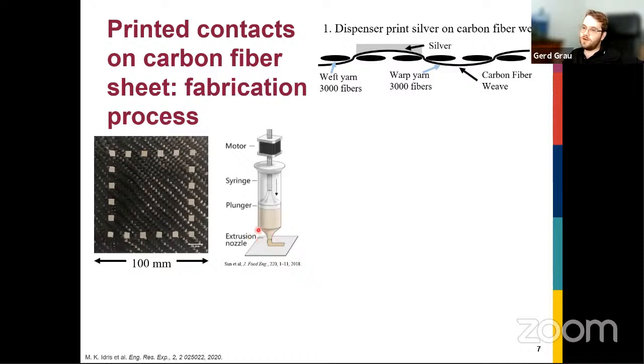But the problem is we need to be in close contact with our substrate here, and this carbon fiber textile is not a very fine textile. These bundles of carbon fibers, they have 3,000, 6,000 fibers in them, so they're fairly rough, they're fairly thick. And you can see here in this sort of side view cartoon, you have these fibers or these bundles of fibers going into the page and running across. And so the problem is that this nozzle can get entangled with stray fibers. So we have to increase the standoff distance between the nozzle and the substrate. And so we have to optimize and understand the printing parameters that allow you to still print in these challenging conditions.